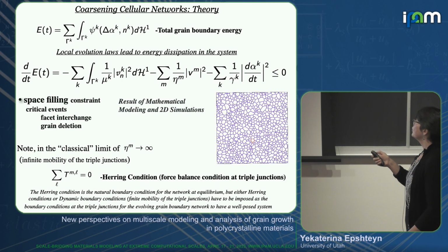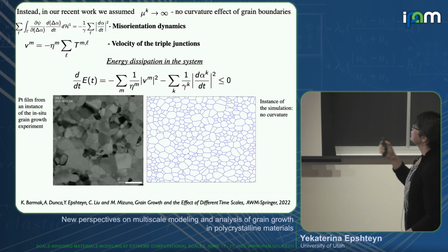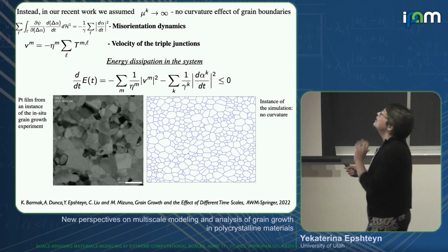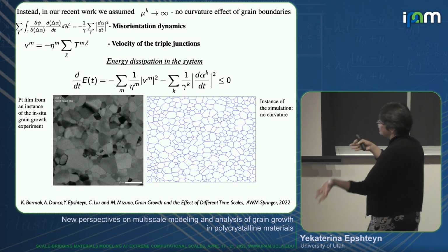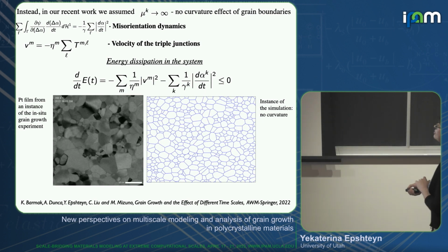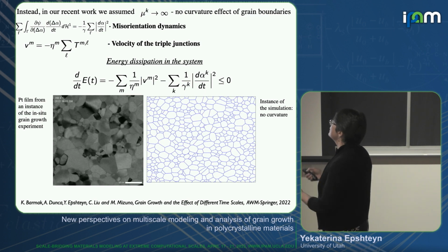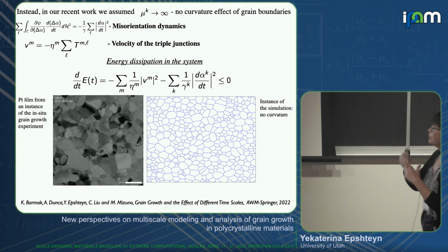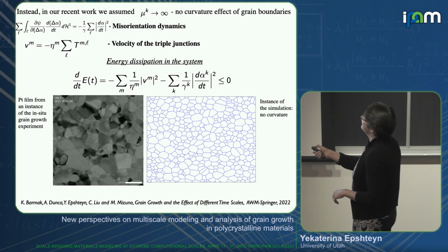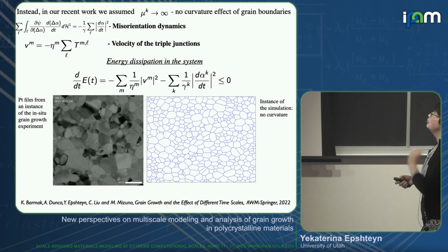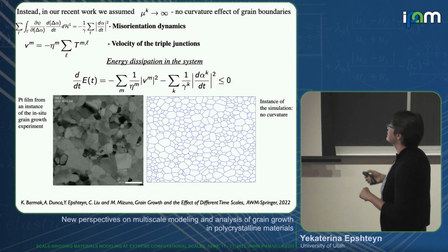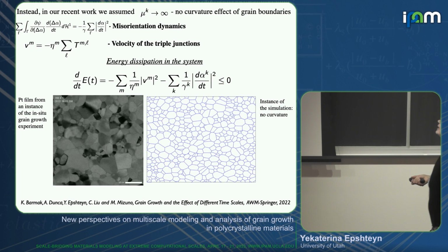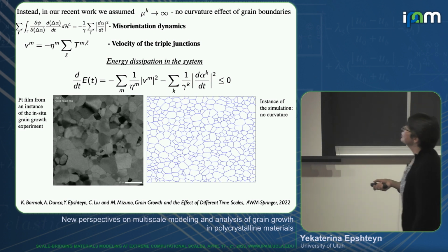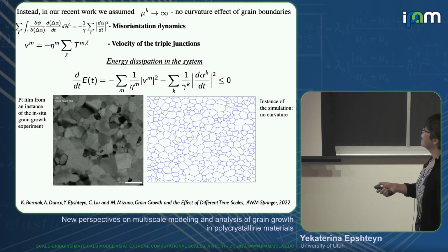In our approach, we actually took a slightly different perspective, at least theoretically. Numerically, we will consider all three relaxation time scales, but theoretically, we decided to relax the dynamics of grain boundaries themselves by setting mobility of grain boundaries to infinity. So what it does, your curved grain boundaries become straight lines, and the entire grain growth is really defined by what happens at triple junctions and by dynamics of misorientation.